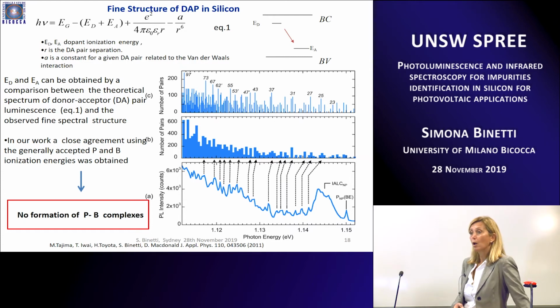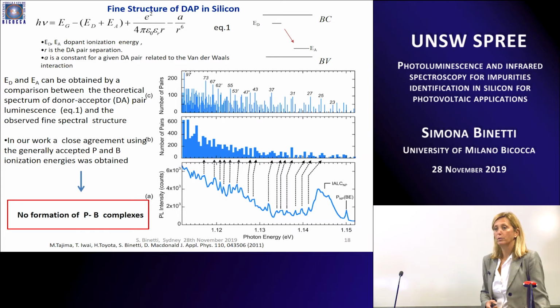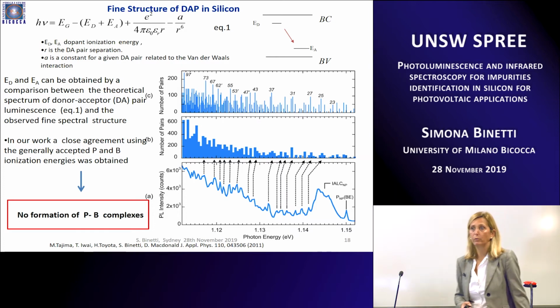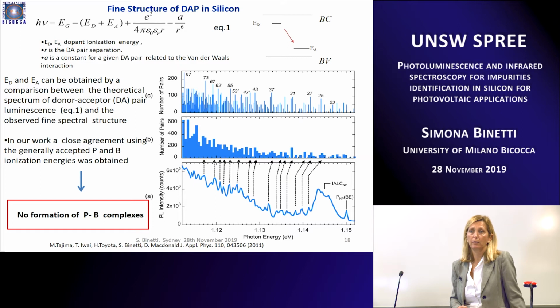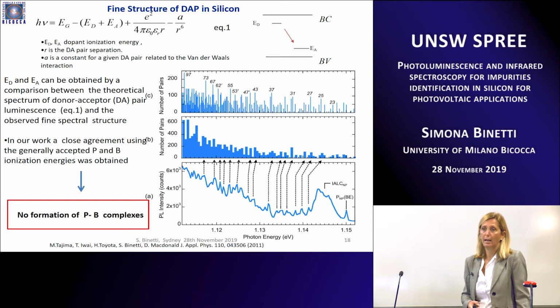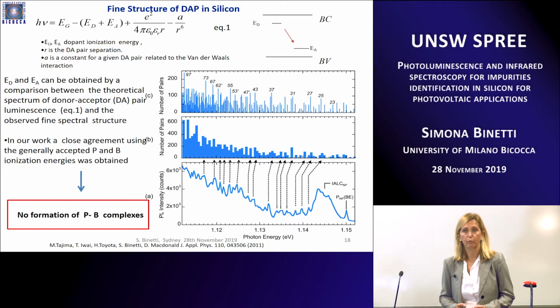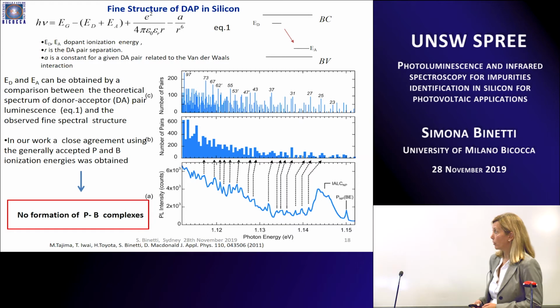And this was quite important at the time, because probably you remember that there were quite strong debates about the fact that in compensated material you have less light degradation effect, because there was a sort of competition between the formation of boron and oxygen and boron and phosphorus complexes. But by this work we have seen that if you have both boron and phosphorus, there is no possibility of formation of boron and phosphorus complexes.